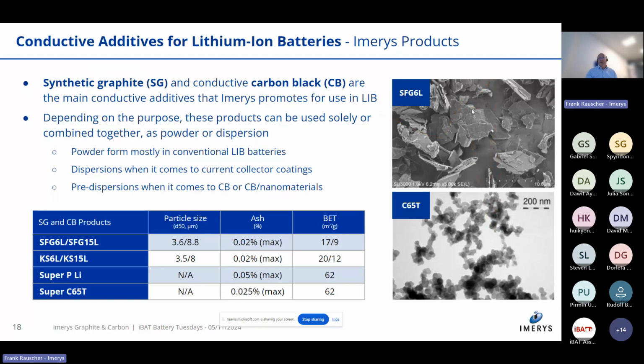We make different types of synthetic graphite. SFG is a graphite with a very high degree of crystallinity. L indicates that this has a high purity design for the lithium-ion battery market, and the number 6 indicates the D90 of those high aspect ratio particles, which is, of course, a bit of a theoretical value.